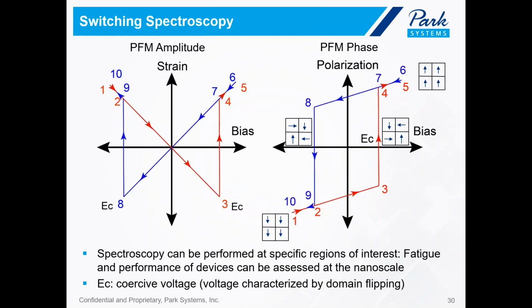So finally, I want to show you another capability of PFM, that is switching spectroscopy. In this technique, you can monitor the PFM amplitude or the PFM phase while sweeping the applied bias. The resulting hysteresis curve can provide localized information with respect to the switching properties of the piezoelectric material that we're looking at. On the left, we have an example of an ideal system's PFM amplitude or strain response during a voltage sweep. You can see that as you increase the bias, you have strain, and then as you decrease bias, it flips.